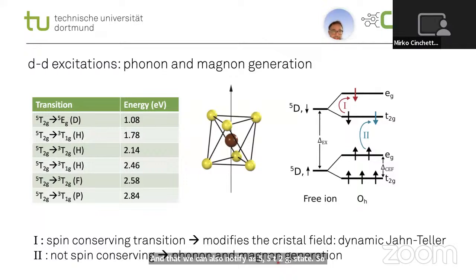Now, what are the excited states of this multiplet of 3d6 electrons? These excited states correspond to our dd transitions. And here you see the energies of the various dd transitions that I was introducing before. If we concentrate on the first one, of course, this is an excitation of a multiplet of 6 electrons, but you can always think about this transition as made of contributions of single particle excitations. And for the first transition, the largest contribution comes from the transition from the t2g to the eg orbital. So basically, when you do this transition, you are modifying the crystal field.